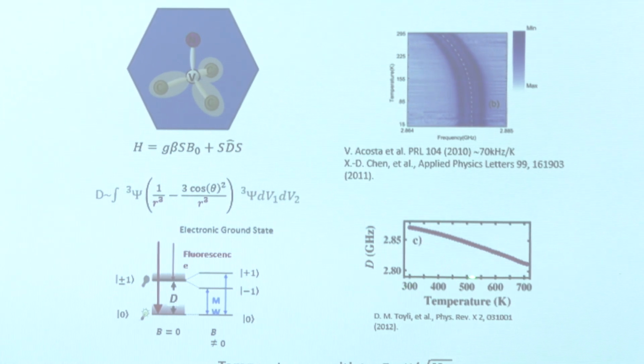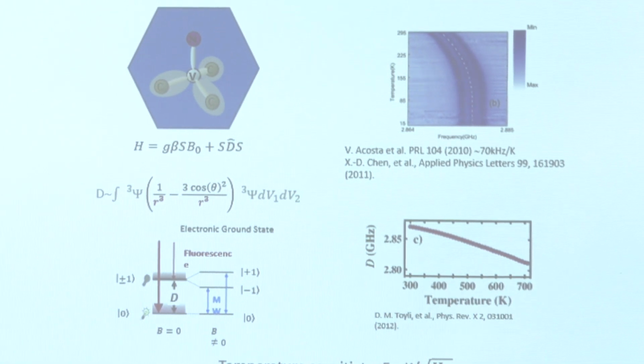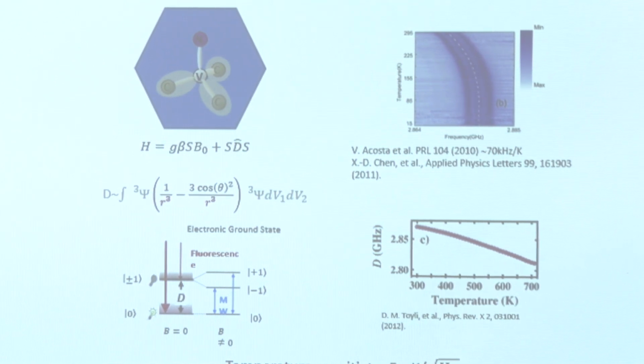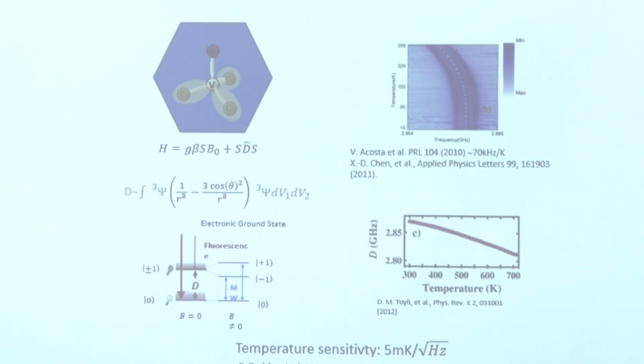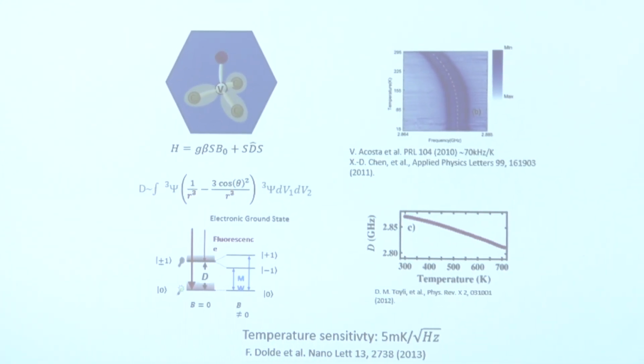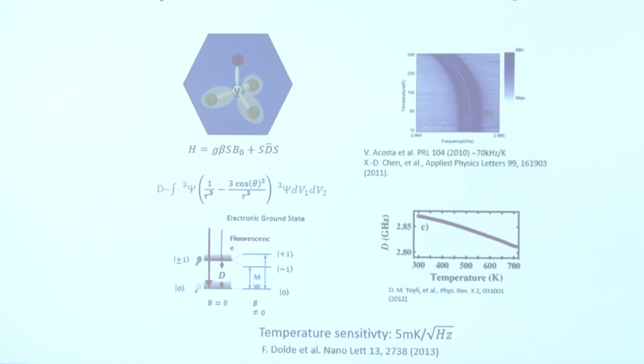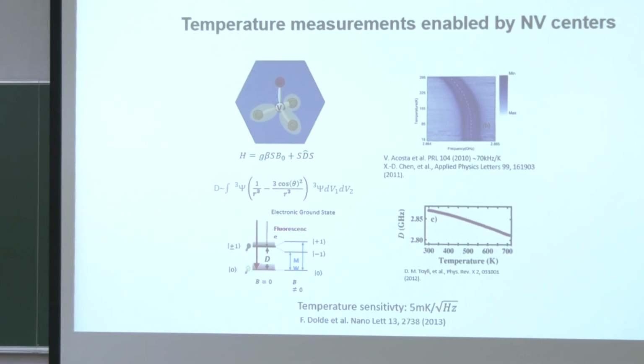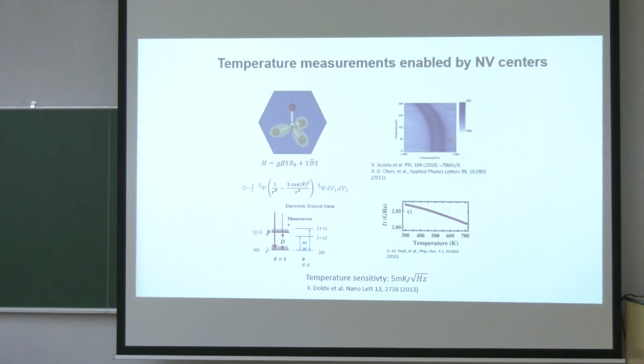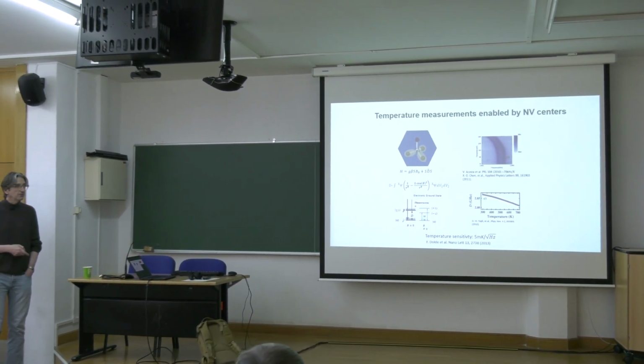This was measured by the Dima Budker group, and there is a shift of about 80 kilohertz per degree Celsius. The diamond lattice expands, and that creates an 80 kilohertz shift per degree Celsius on the spin transition. Now you can think about whether it's big enough or not. Remember, it should be compared with coherence times. The lines are sharp at this scale, kilohertz, with millisecond coherence time. And now you have a shift of 80 kilohertz per degree Celsius. That provides you an instrument to track the temperature with very high precision and very well calibrated. In a bulk diamond, a precision of 5 millikelvin per square root of hertz was demonstrated by your Prof group, but not with this precision yet for nanodiamonds.